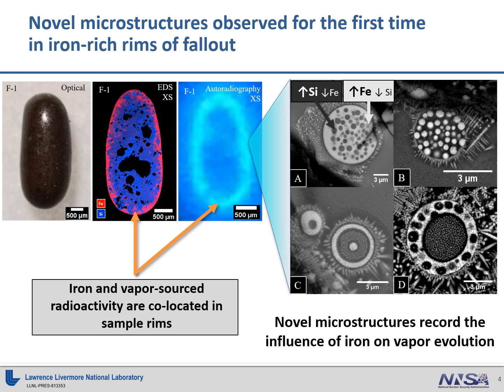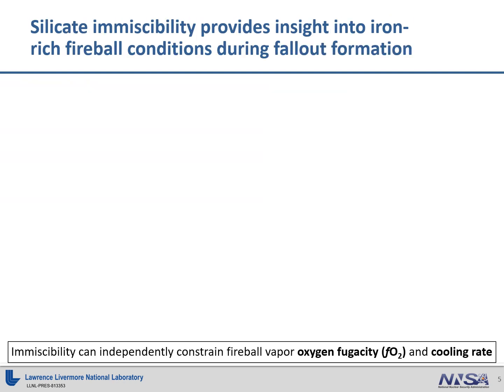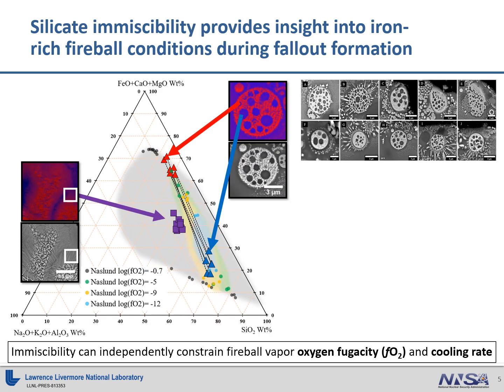These textures suggest formation by high-temperature multi-component liquid immiscibility, analogous to how oil and water separate out into two separate liquids. Thus, these structures preserve a record of that phase separation process and conditions under which it occurred, including the evolution of the iron-rich radioactive vapor. The two-phase compositions of these microstructures are consistent with multi-component liquid immiscibility observed in the geologic record.